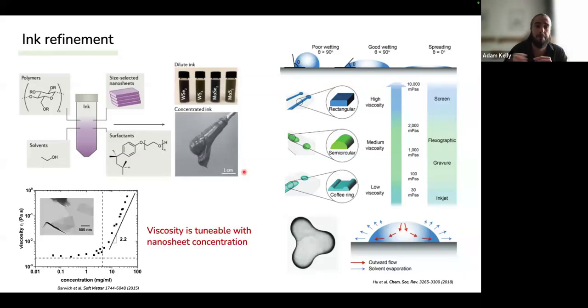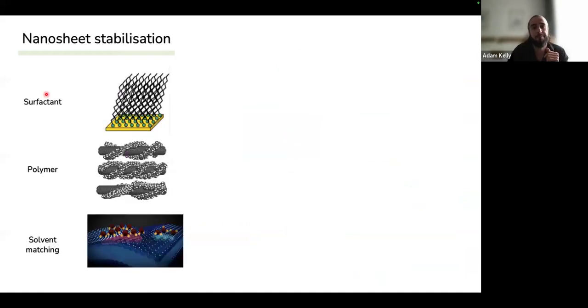tuning with your surfactant. Now, what we also found is that the viscosity itself is tunable with nanosheet concentration. So when we're adding in these nanosheets, what we find is that above a certain concentration, the viscosity starts increasing by orders of magnitude. Now, this is good because it means we can just add in more active material, and we don't need to use as many polymers, because when you have polymers in your network, you also need to get rid of them after they're printed.